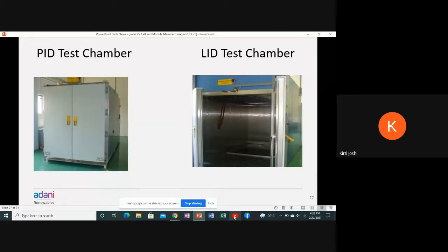So to check the degradation, the modules are placed inside the chamber with the light such that the power generated by the module should be 60 watt hour. And once it generates the 60 watt hours, the modules get taken outside from the chamber, and again the degradation of the module is to be checked, and also again it should not be more than 2%.